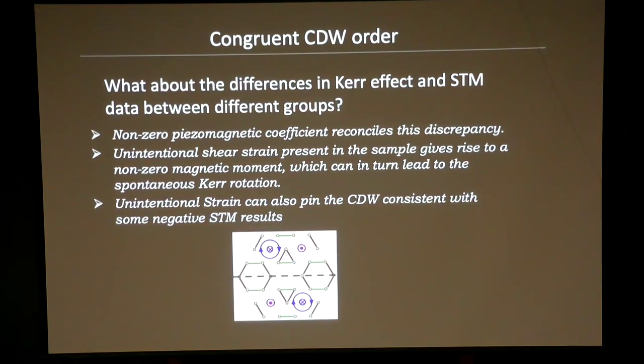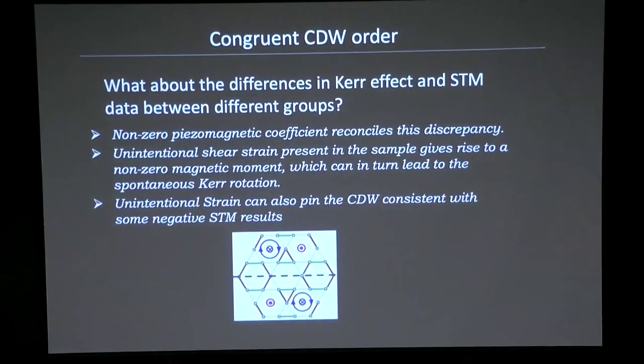So let's say we've established that there's broken time reversal symmetry. How do we now reconcile these different measurements that different groups have seen over the last few years? And actually there's a simple answer to that question. This material, as we've already shown, is strongly sensitive to lattice parameters and to lattice distortion. That means that any unintentional strain in the system is going to actually pin the charge density wave. For example, let me show you this. If you have shear strain in the system, then you can actually have a net magnetic moment, because now you no longer have this axis of rotational symmetry, and then you can have this being stronger than this, and that will give you a net moment.